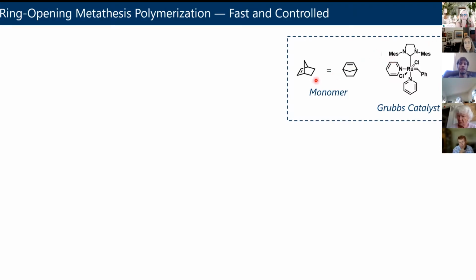And we use a monomer called norbornene. These are two depictions of the same norbornene monomer. It's a bicyclic ring system, which means there's two rings that are fused together. And importantly, it has this double bond in it. So you can see this is more of a three-dimensional picture on the left. This is more of a top-down projection on the right. Importantly, norbornene, because of that double bond being constrained in the ring, it has a lot of ring strain. And so when it's exposed to this catalyst, the catalyst can really quickly react with it. And it can polymerize it to build up a polymer, where our monomer or our building block is norbornene.